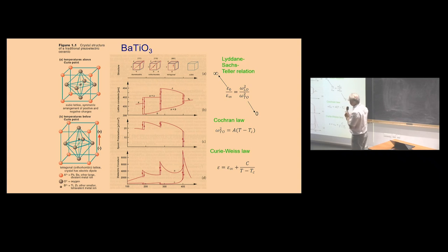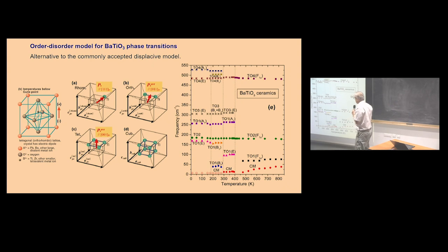So in barium titanate, you know, there are 3 structure phase transitions: cubic, tetragonal, orthorhombic, rhombohedral. Polarization has jumps. Permittivity has again peaks, again due to such phonon softening, it looks like. But what was observed is that in barium titanate there are 2 or 3 optical phonons, and they show negligible temperature dependence.